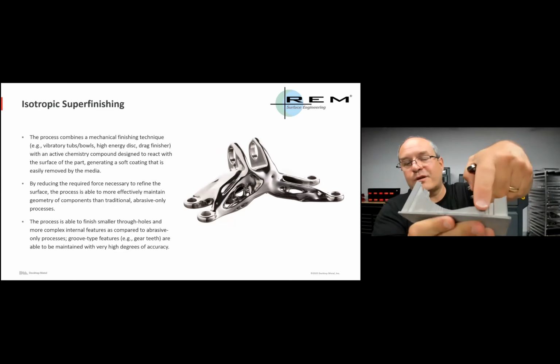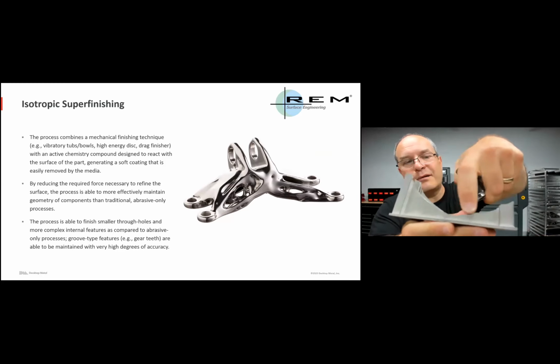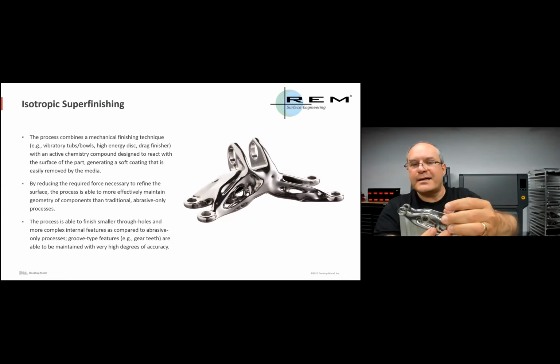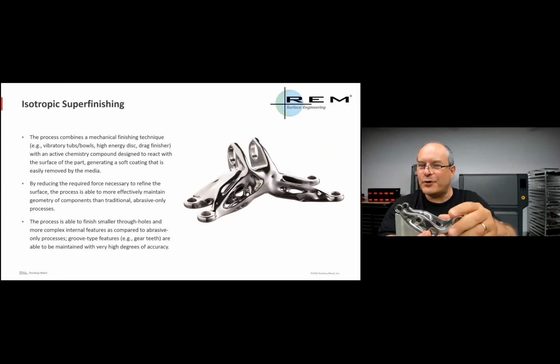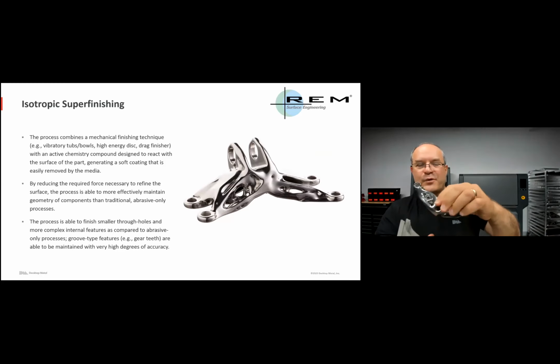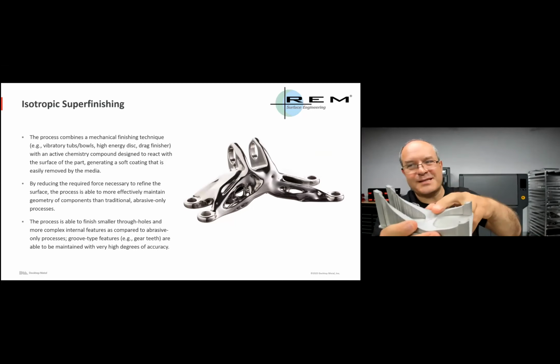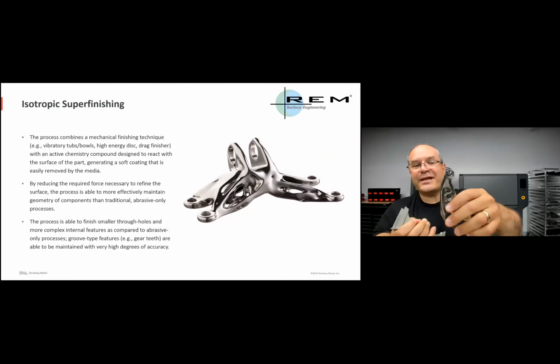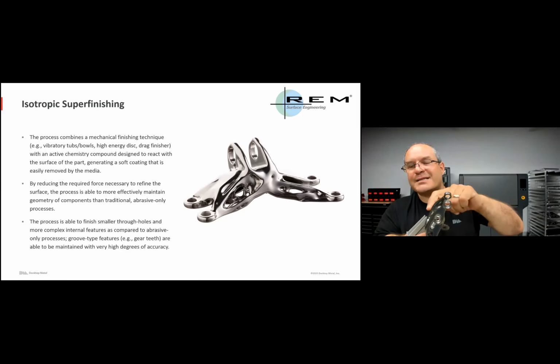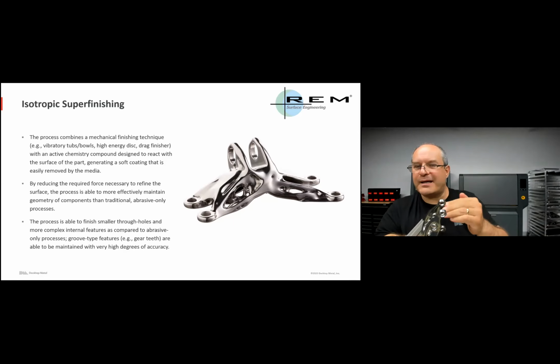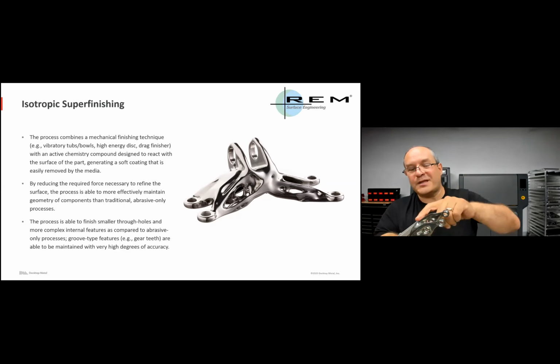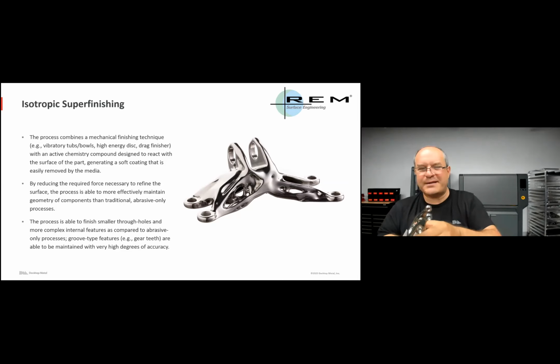The part started out with literally this exact kind of matte surface where you can see the layer lines. It's immersed in a fluid. That fluid reacts with the part that started out with this kind of finish. And then by reacting with it, just that top surface becomes soft. It's like a conversion coating, becomes soft and much easier to remove using the vibratory bowl or the high energy disc method.